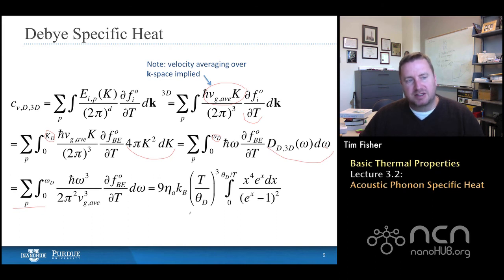We also, because we have a three-dimensional problem, and we're going to take the acoustic branches, the three acoustic branches, we have one that's longitudinal and two that are transverse. We put those in here and we evaluate. And again, we can express this specific heat in terms of the unit cell density, that's eta sub a, and then a bunch of other constants. This integral, we're going to need to evaluate. We'll do that on the next slide. And then the Debye temperature, and we find that we have a T temperature to the power three dependence. So specific heat increases in a cubic way. Now, there's still a little bit more to do here. This integral has a temperature dependency to it as well. So we'll hold off on making that a conclusion, and we'll talk about where it does apply in that T to the power three dependence.